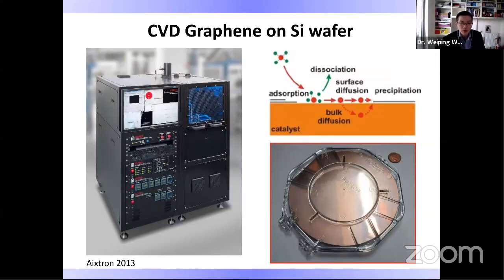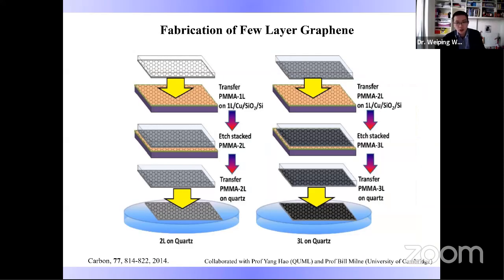So the more advanced method has been developed by Cambridge University and other research groups working on CVD growth of graphene and 2D materials. Nowadays, it's possible to grow graphene and 2D materials at a wafer scale, talking about 8-inch or even meter scale. During my time at Cambridge, I worked on stacking or transferring CVD graphene